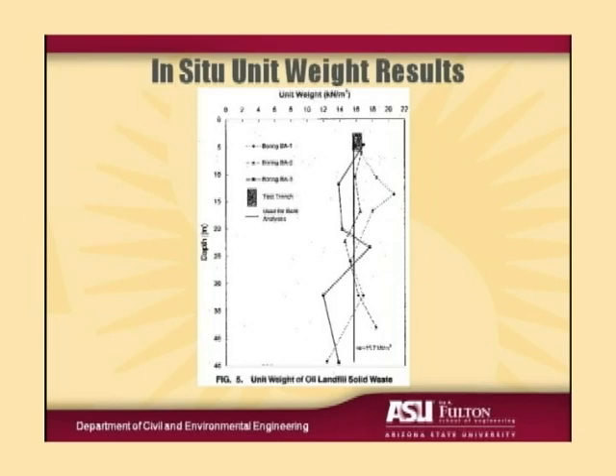For engineering purposes, we also show the unit weight we got in that large test trench at the surface. For engineering purposes, we characterize the unit weight as 15.7 kilonewtons per cubic meter. That's about 100 pounds per cubic foot for those of you who still like to work in the imperial system. Importantly, that's significantly higher than the unit weights that people used and still use in practice today.